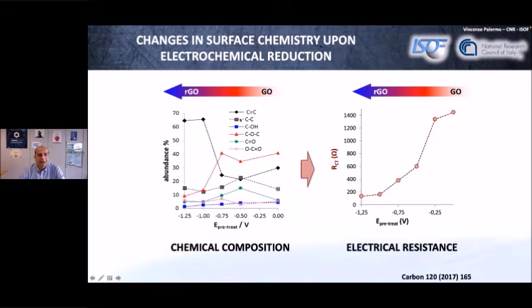And the most dramatic change is that the number of C=C double bonds increases. And these, as I said, indicate that we are restoring this hexagonal lattice forming graphene. And these are also the bonds that are responsible for electrical conductivity. So when we go from right to left, the number of these double bonds increases. If we measure the charge transfer, so the electrical conductivity or the resistance of the electrode, you see in the right graph that the electrical resistance also goes down. So there is a direct correlation between the chemistry of the material and its electrical properties. And we'll talk more in detail about this later on.